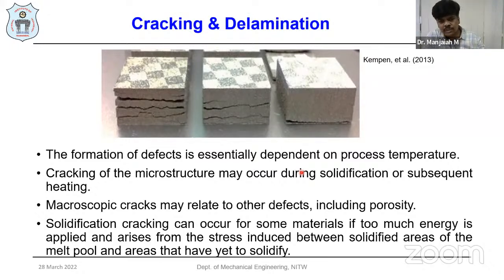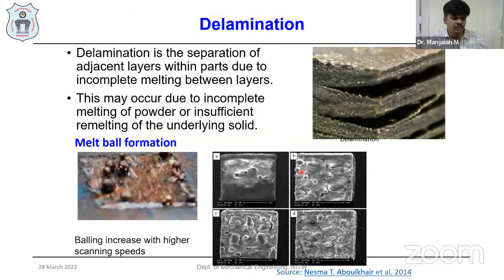And solidification cracks may occur for some materials if we are supplying too much energy to melt the materials, which will give rise to residual stresses induced between the solidified or remelted areas and those yet to solidify. In such cases, we are going to have these kinds of cracks in the solidified or fabricated components. And the other one is delamination.